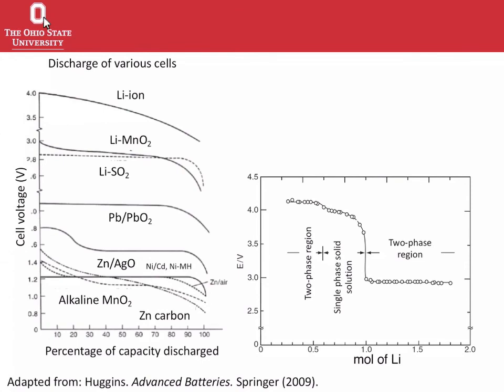And you can see here with real data, cell voltages as a function of the percentage of capacity discharged. You can see for different materials, they behave differently. So you can see, okay, there's a two-phase region here, there's one phase, here's something that looks like one phase-ish. It's like this forever sloping. And what you expect at one cycling rate might not be reproducible for different cycling rates. So for a different C rate, right?